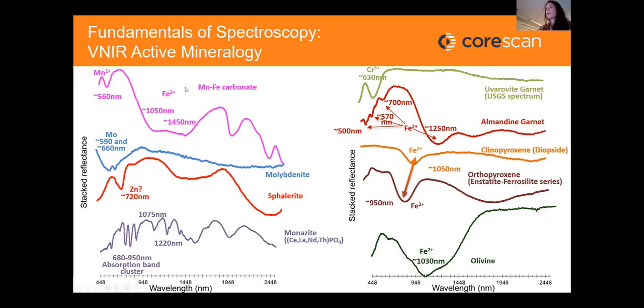Over here in pink on the top left, we have a carbonate spectrum. And you can see manganese is being incorporated into your carbonate because you have the development of a feature at 560 nanometers. Another feature that we see really frequently, almost in every project, is the development of a very large absorption doublet, maybe trough at this point, between 1050 and 1450 nanometers. And that's due to iron being incorporated into our carbonate.